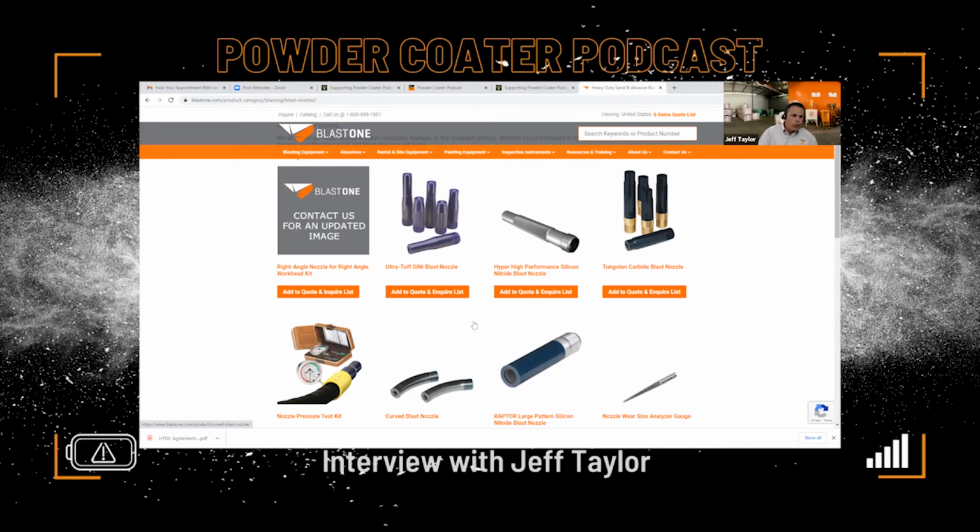So you're probably going to get 200 hours out of a tungsten carbide nozzle, where you're going to get 400 to 600 out of an ultra tough nozzle. When you drop an ultra tough nozzle, it has a urethane exterior. It absorbs all the shock, and silicon nitride isn't nearly as brittle, so they don't crack. They're a little more robust as far as dragging them or dropping them in the shop. So that's what you would see. It'd last you a little bit longer, it's got better wear on it, and it's a little more durable.